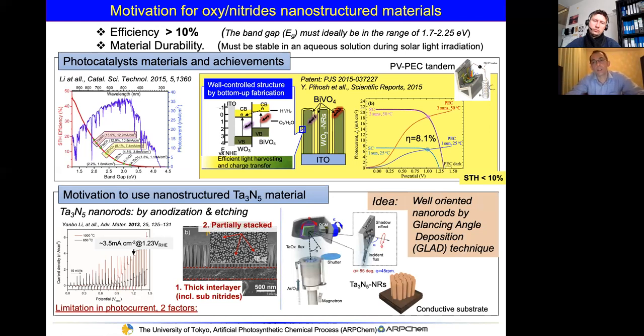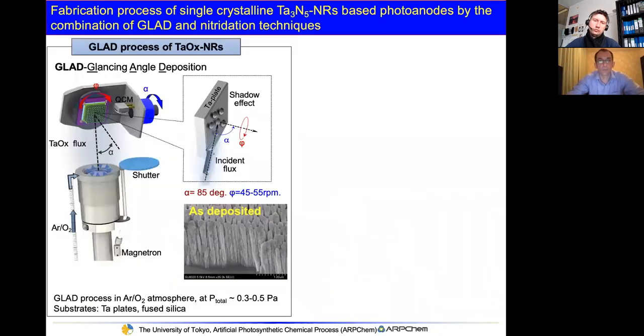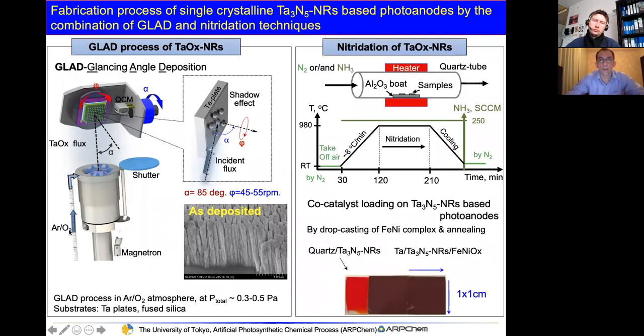So for that reason, the idea is a well-oriented nanorod, which can be grown by the glancing angle deposition technique. The advantages of that technique are that the prepared nanorod has no interlayer, and if we develop good parameters, we don't have any stacking of the nanorods. This is just schematically shown how we deposited the nanorod with the main parameters. And this is a SEM image of the as-deposited material. This is still amorphous because we are working in argon and oxygen plasma. So then this sample should be nitridized.